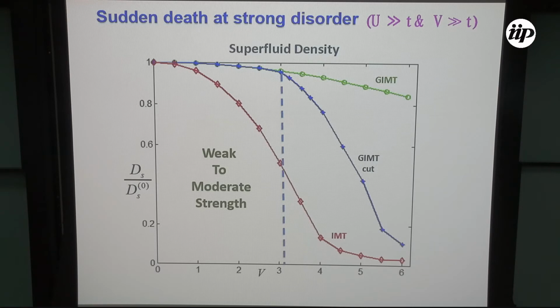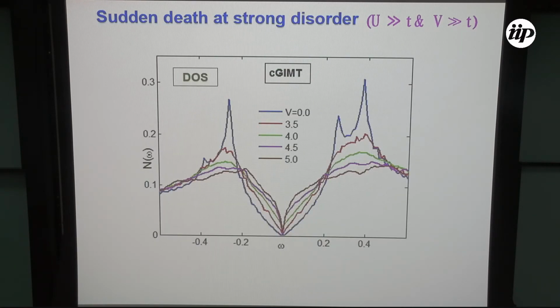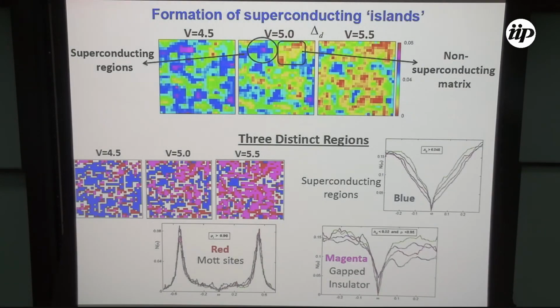If you look at the density of states, it was quite robust for weaker disorder, but if you make the disorder very high, above the bandwidth, you will see in-gap states forming here. And the coherence peak also goes down. To understand what is actually going on, we look at the formation of superconducting islands if you have very strong disorder. What will happen is that you will form superconducting islands like this, where these blue regions are highly superconducting. So in these regions, the superconducting order parameter is high, but they are in a matrix which is non-superconducting, this green and red region.